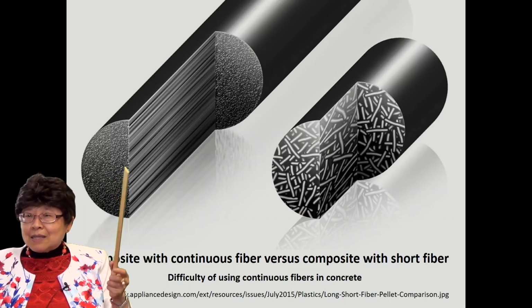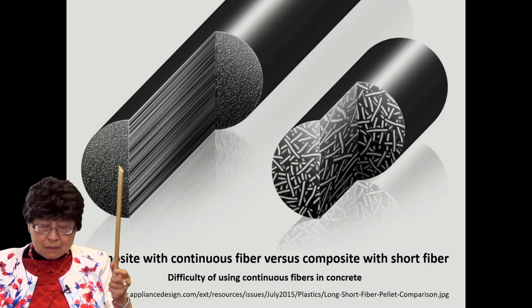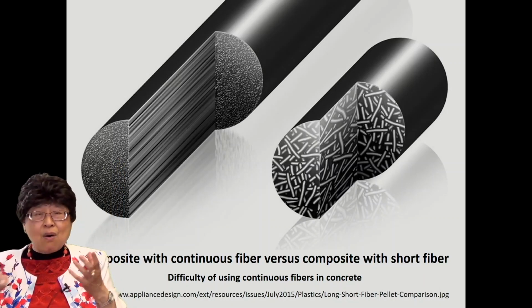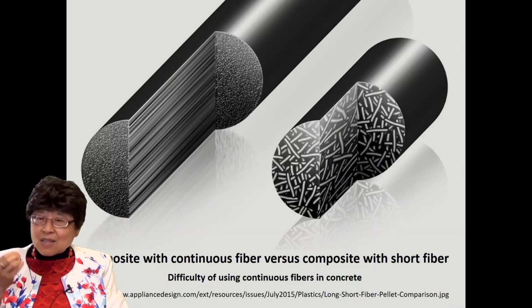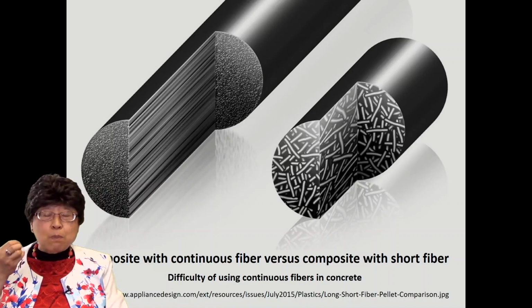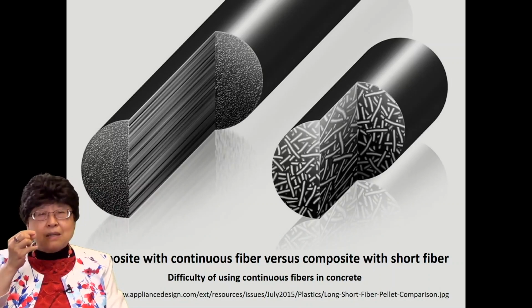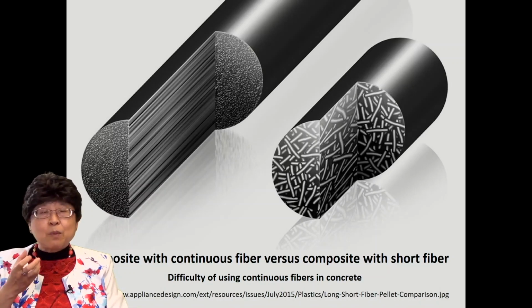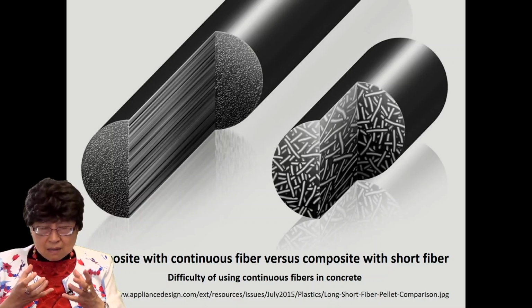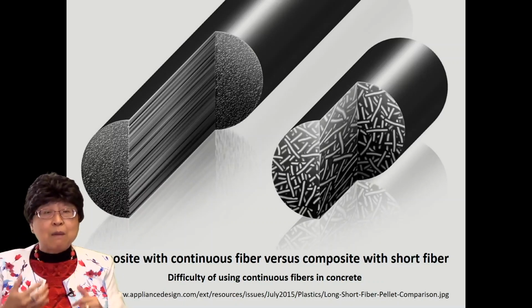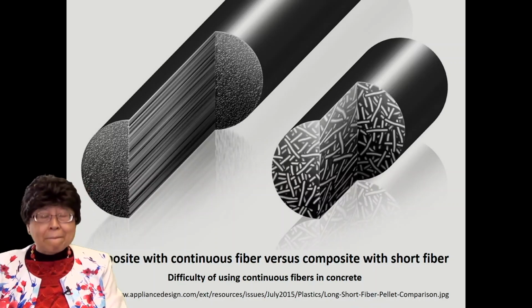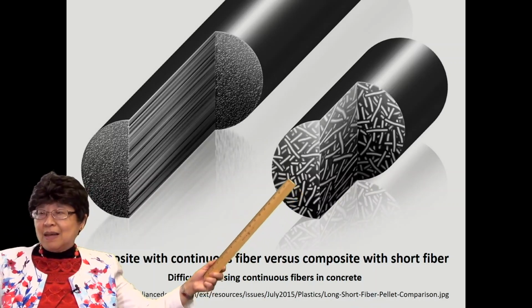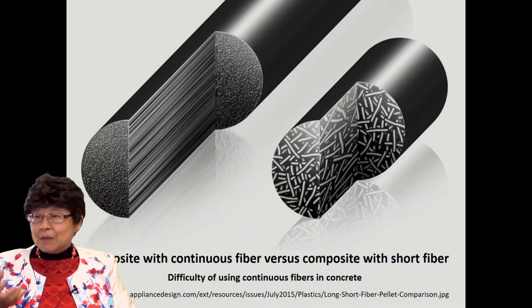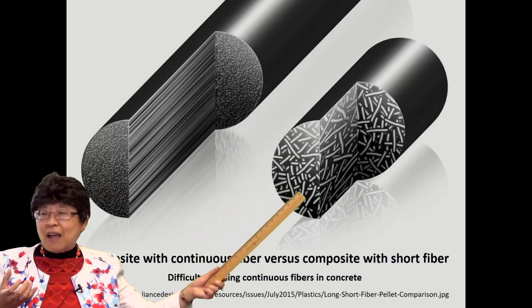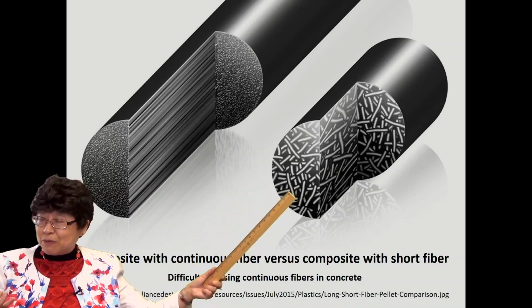Not only that, these continuous fibers are in the form of tows or bundles. It could be 12,000 fibers in the tow. And the cement is not so fluid, and it's hard for the cement paste to penetrate the space between the adjacent fibers in the tow. So you would end up with a situation where there's a lot of porosity due to the emptiness between the fibers in the same tow, due to the fact that the cement paste cannot get in. But if you have short fibers, that problem is much less. The dispersion of the short fibers can be enhanced by the silica fume, as I mentioned before.